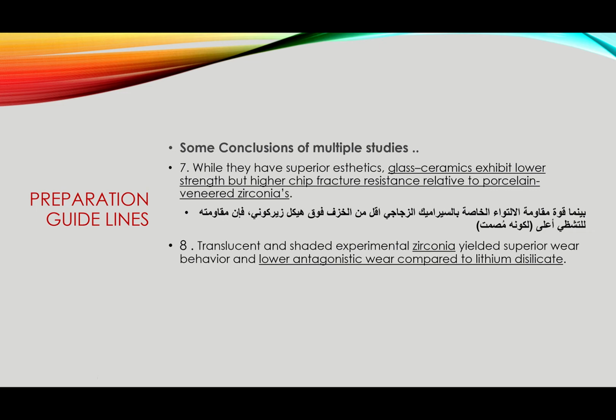Translucent and shaded experimental zirconia yield superior wear behavior and low antagonist wear compared to lithium disilicate. All right, so zirconia wears the opposing dentition less than lithium disilicate. So translucent and shaded experimental zirconia yield superior wear behavior and lower antagonist wear compared to lithium disilicate. So the wear of the opposing dentition for a zirconia is lower than for a lithium disilicate.